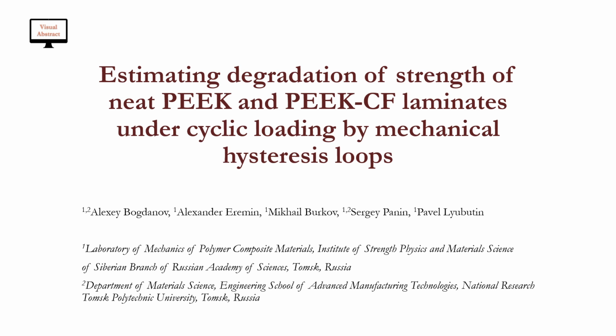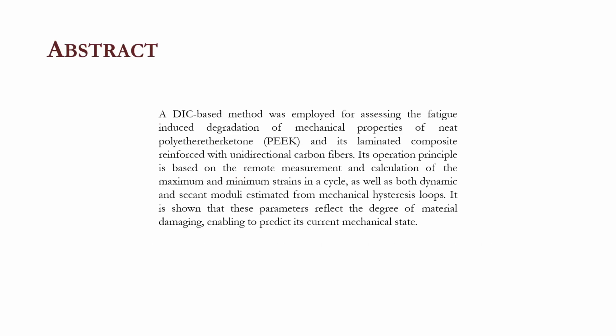Hello dear listeners, I would like to present you a report on the topic: estimating degradation of strength of neat PEEK and PEEK CF laminates under cyclic loading by mechanical hysteresis loops. In this work, a DIC-based method was employed for assessing the fatigue-induced degradation of mechanical properties of neat polyetheretherketone and its laminated composite reinforced with unidirectional carbon fibers.